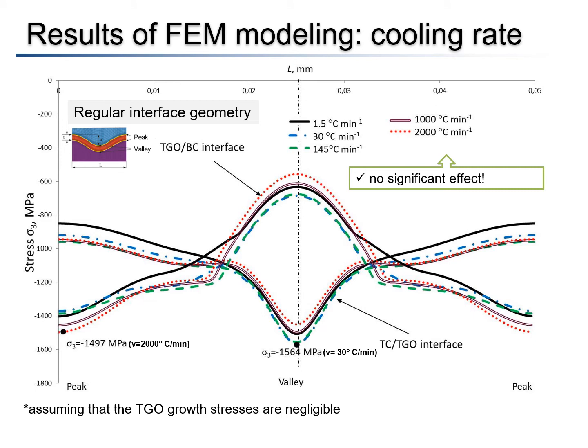In our previous study, it was shown that for the TBC system with the regular interface geometry with uniform thickness of thermally grown oxide, the cooling rate has no significant effect on the residual stresses values in TGO. Five various cooling rates from the stress-free temperature 1100 degrees C to room temperature were considered, so from really slow to really fast. You can see on this slide the values of minimal principal stresses, so compressive thermal stresses, depending on the wavelength of modeled representative microstructural areas.